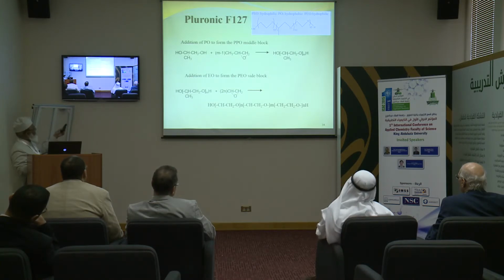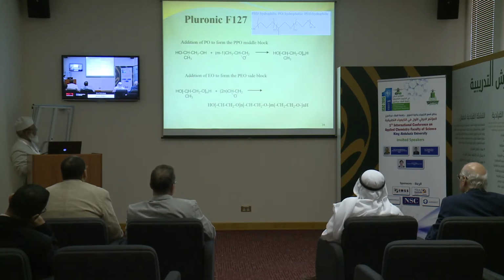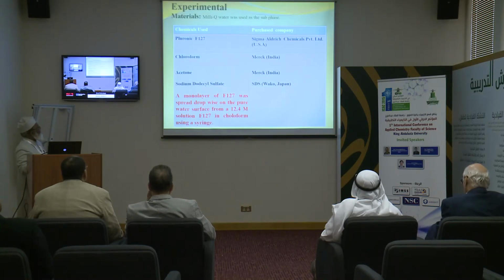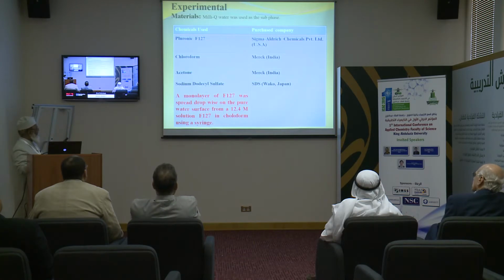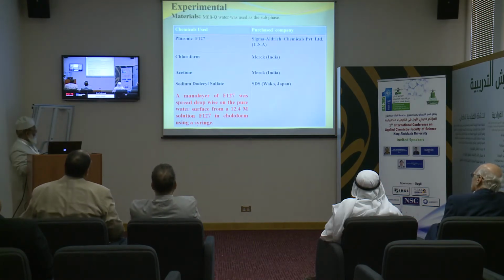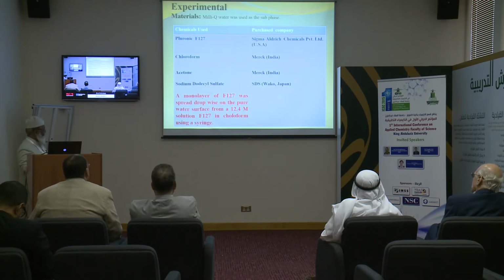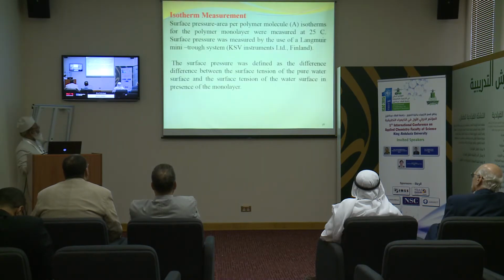tri-block copolymer, and this is the protocol regarding the formation of it. These are the various materials which have been used for the preparation of the monolayer. A monolayer of pluronic was prepared by spreading drop wise on the pure water surface from a 12.4 molar solution in chloroform using a syringe. Surface pressure versus area per molecule isotherms for the polymer monolayer were measured at 25 degrees centigrade, and we used the Langmuir MiniTrough system for this.